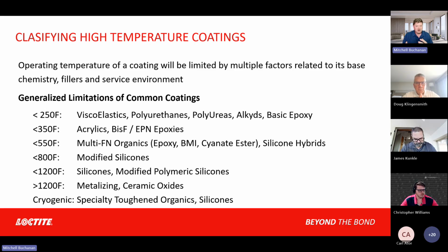And then once you get above that 1200 Fahrenheit range, really this is where metallizing type coatings, thermal sprays, zincs, aluminum, magnesium, right? That's going to be the primary solution. And then also you get into thermal spray silicone or ceramic oxide, so aluminum oxide and various different ceramics, instead of just pure zinc metallizing.